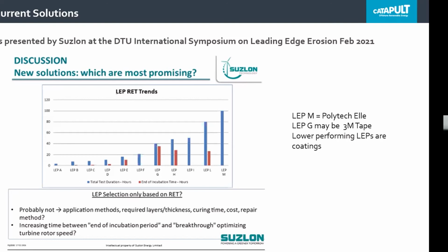Interestingly, Suzlon's comments at the bottom: are they basing their decisions only on how long the coating performs in the rain erosion test rig? And they're turning around and saying not. So they're not just looking for products that have this really high performance in the rain erosion test rig, they're also looking at how this is applied onto a wind turbine, both in production and in repair.